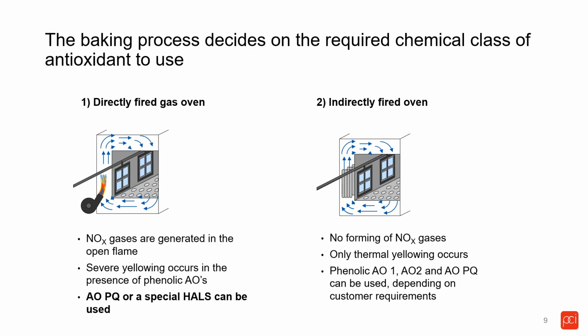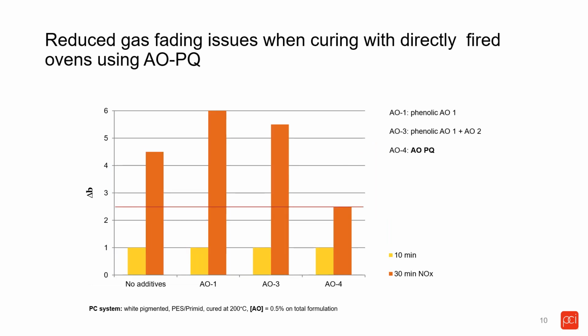So here we see the performance in NOx, and just to confirm what we mentioned earlier, when we are using a phenolic antioxidant, our yellowing, in this case at 30 minutes, in NOx is really even worse than with no additive stabilization. And we see that AO3 is not much better, but really AO4, which is our phosphite-based antioxidant, significantly reduces the yellowing or the discoloration caused by NOx in a direct gas oven formulation.